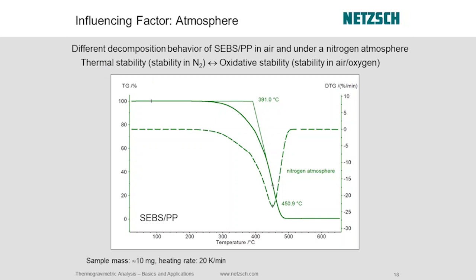Okay, so we look here. This is our first heating, 20 degrees a minute. We have a 10 milligram sample, and there's no mass being lost. Then finally, we get to around 300 and some degrees, and you see it start to break from the baseline, and we're starting to lose mass. So there's our classic stair step in the TGA profile. This is the dotted line I told you about, the differential, or the first derivative of the curve. That tells us more easily where the maximum point in the slope is. And here's your onset. Remember, we said sometimes folks want to know what the onset is, where it starts to break from the baseline, where it starts to lose mass. That's your onset, and that's your maximum point, in a nitrogen atmosphere.